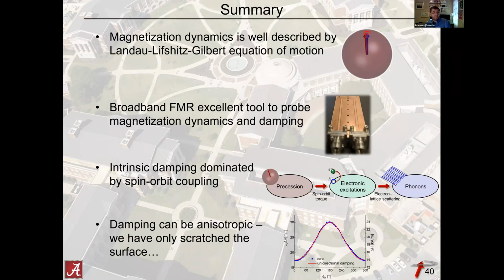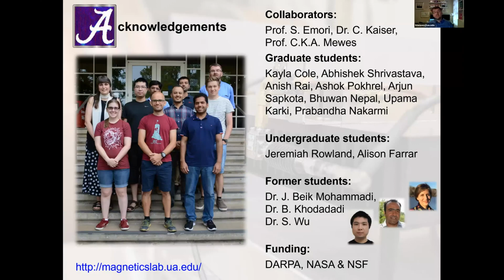I hope I also showed you that damping can indeed be anisotropic, but in this regard, I think we've only scratched the surface. But one also needs to be very careful not to mistake anisotropic damping with contributions that come from two-magnon scattering. With that, I would like to thank all the people that contributed to this work, in particular